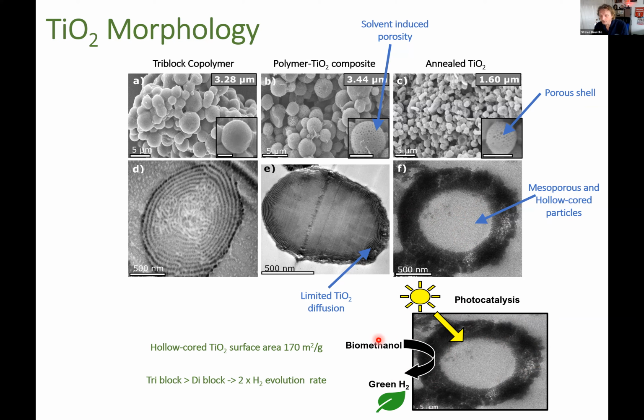Now, the results we've got are very preliminary. People have converted methanol to hydrogen before using photocatalysis. But what we've begun to show is that we can do this very effectively, and that our tri-blocks are much better than the di-blocks, and we get much better hydrogen evolution. So maybe we're on the way to making some structured catalytic materials here that could be of interest going forwards.